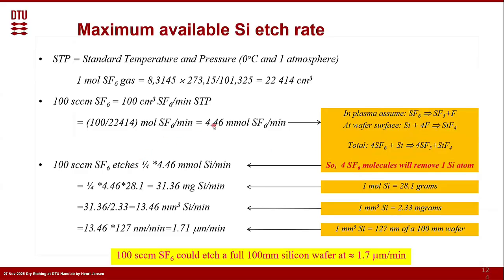We fill that in. So it means that we have 100 SCCM SF6. It can etch then 1/4, that's this 1/4 over here, times this 4.46 millimole of SF6. So 100 SCCM will etch 1/4 times 4.46 millimole silicon per minute. But we know that 1 mole of silicon is 28.1 grams. We fill it in, it means that it is 31.36 milligrams silicon per minute. We also know the density of silicon. It's 2.33 milligrams per cubic millimeter. That puts in this one, and we find with 100 SCCM SF6, we can etch 13.46 cubic millimeter silicon per minute.